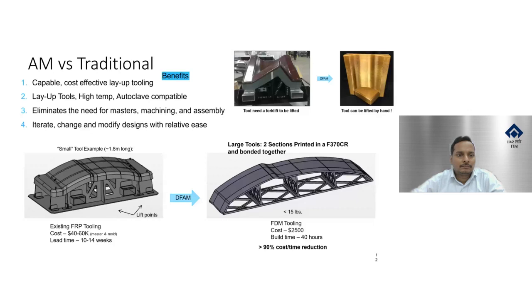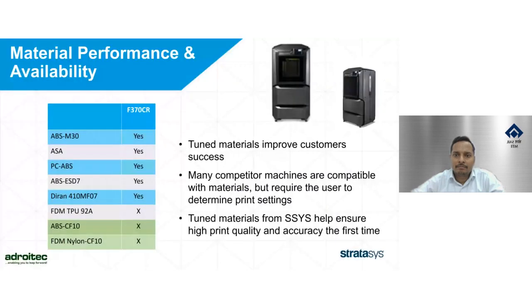So here's the basic differentiation. On the left side, you can see the normal traditional part, which costs around $40,000 to $60,000, with a lead time of around 2 to 3 months. On the right side, we have the part completely printed on the F370 CR and bonded together with special glues. That cost around $2,500, and the build time was around 40 hours. So this is around a 90% reduction in cost and time. That is a plus point for FDM technology. The materials that I talk about are industrial materials.